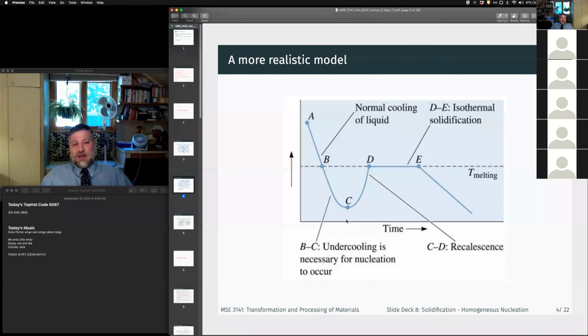I once saw a fantastic demonstration of homogeneous nucleation in cooling in nickel, right? Where they had a really essentially clean amorphous quartz crucible and an alloy that was right at the eutectic temperature. So, you know, the eutectic composition, so at the lowest melting point.